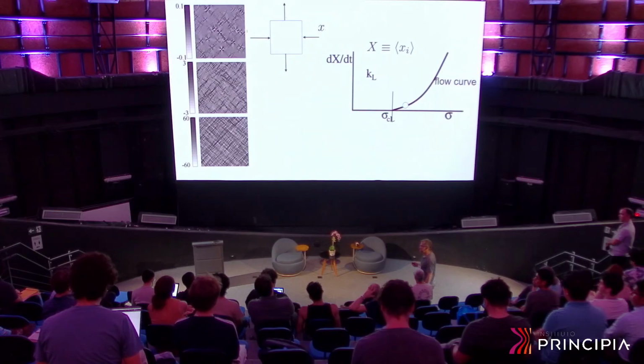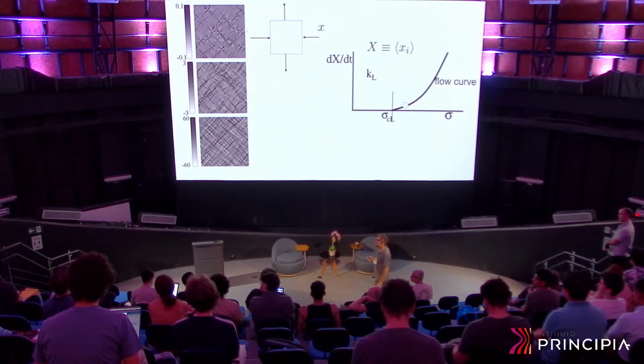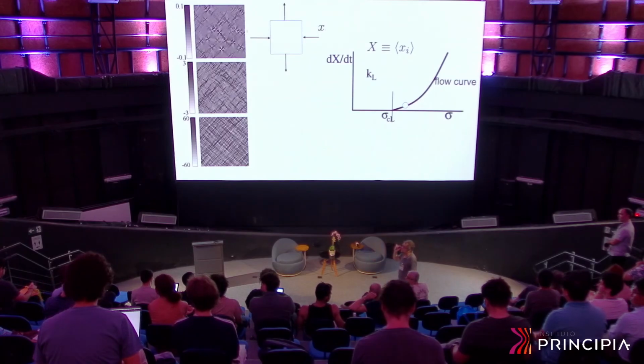Yeah, the point is that your figures are very clearly reminiscent of what is observed in optical microscopy between crossed polarizers when you are looking at defects in lamellar phases, smectic systems. It hints at a layered structure underneath. So you have spherulites, and then you have oily streaks, or things that are quite...